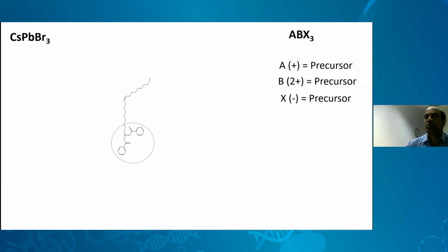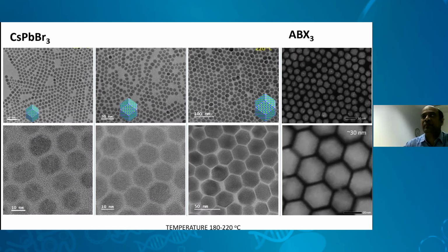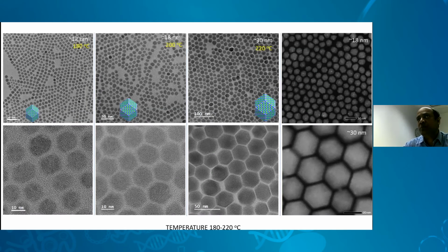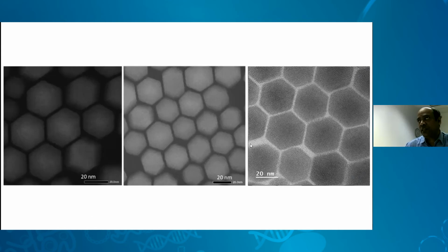You see the cube structure, which has been widely studied, has changed to a new nanostructure having 12 facets. Now again, you see here 180 degrees, 200 degrees, 220, whatever. Maybe you change the temperature, the size changes, but the shape remains the same: 12 facets are here. Again, here I will show a slightly larger view, the HAADF images as well as the TEM images.